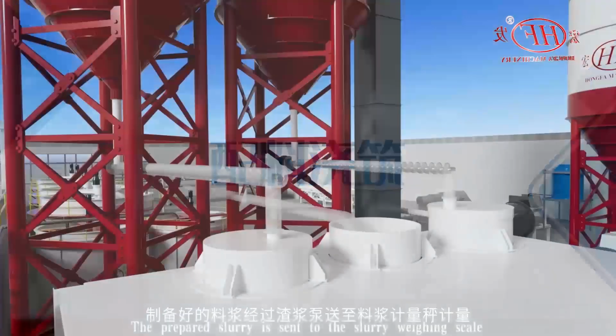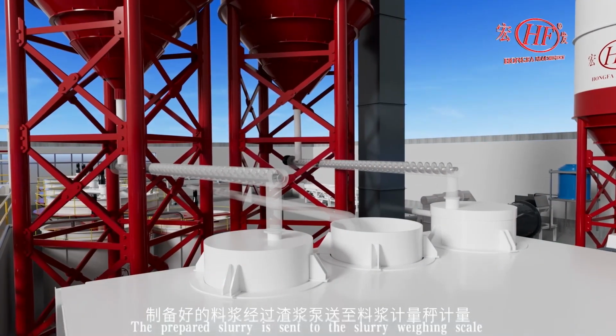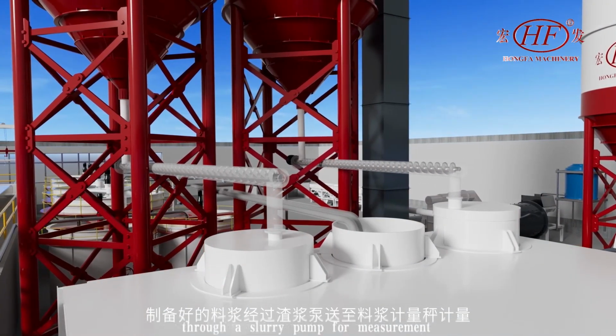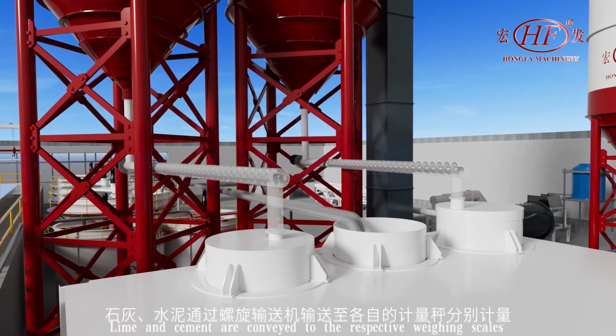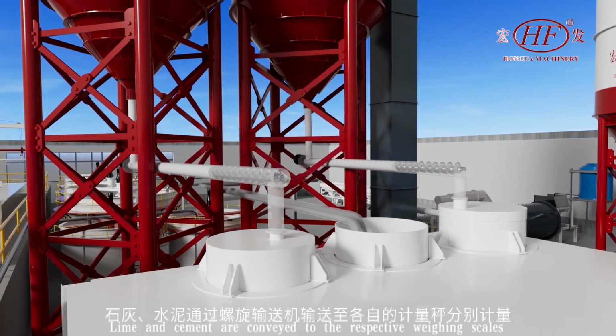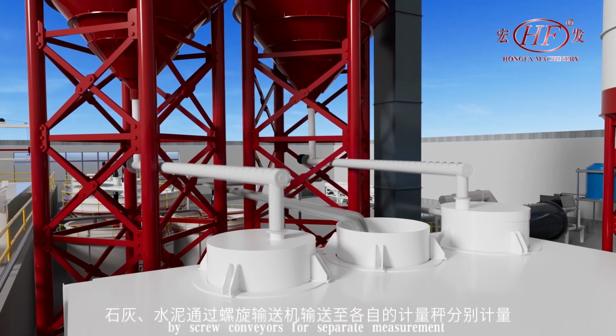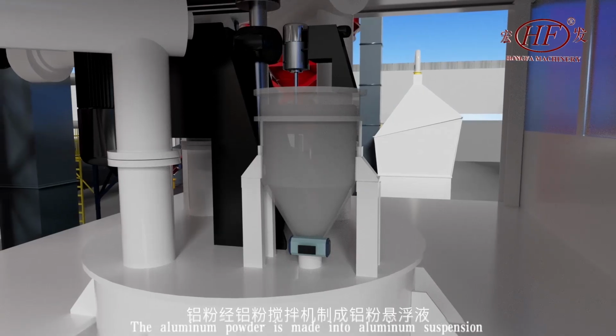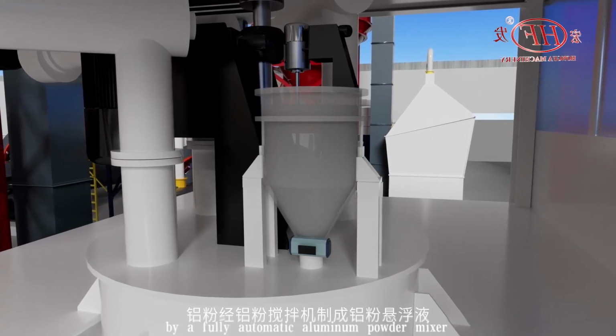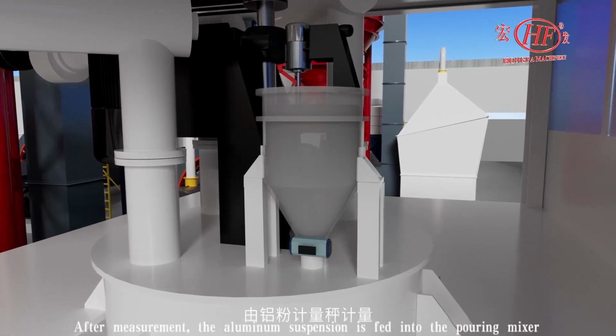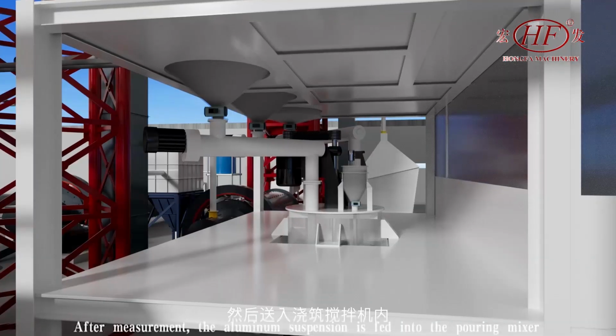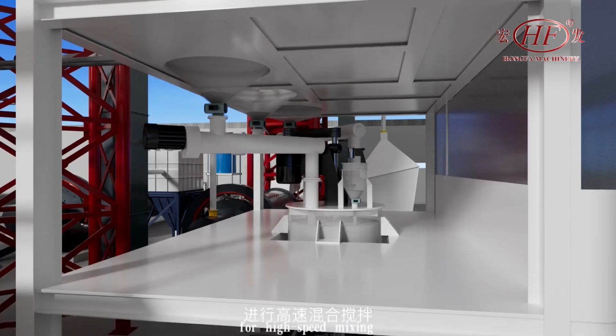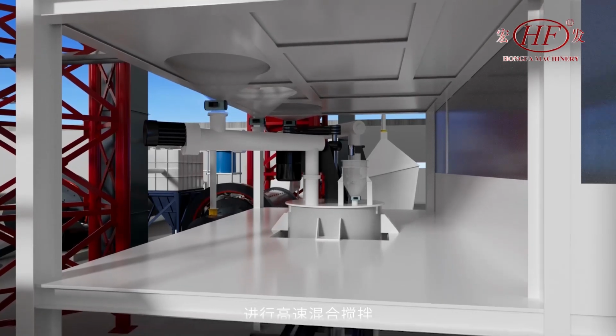3. Batching and pouring. The prepared slurry is sent to the slurry weighing scale through a slurry pump for measurement. Lime and cement are conveyed to the respective weighing scales by screw conveyors for separate measurement. The aluminum powder is made into aluminum suspension by a fully automatic aluminum powder mixer. After measurement, the aluminum suspension is fed into the pouring mixer for high-speed mixing.